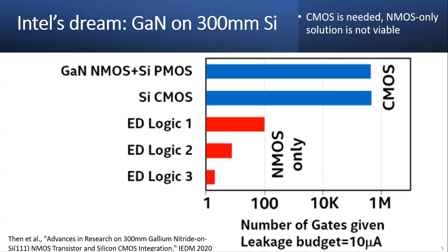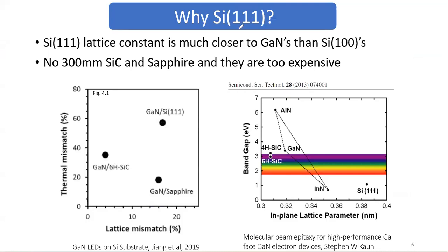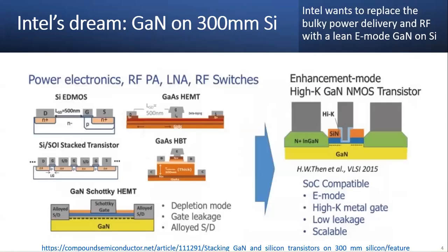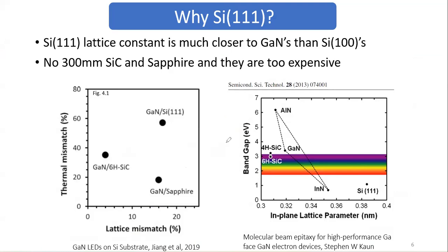The first question that comes to mind is why silicon 111? If you look at the picture here, the gallium nitride has to sit on a piece of wafer, right? A 300 millimeter wafer. So you could have multiple options, of course. If you survey the industry, gallium nitride currently can be done on silicon carbide or sapphire. But these are all like 6 inches, 4 inches. Silicon carbide, you can do 6 inches. Wolfspeed can do 8 inches. And sapphire pretty much is 4 to 6 inches only.